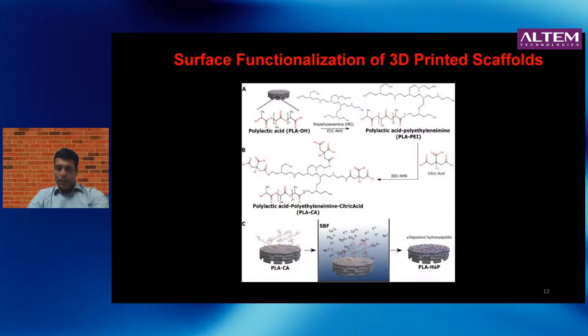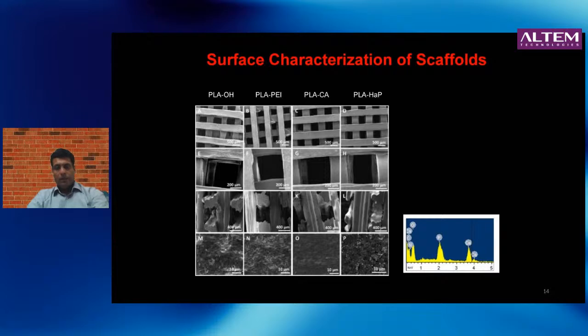Now, why citric acid? Because naturally it's present in small amounts in bone tissues, and its role is to help in the nucleation of calcium phosphate. So when we took the citric acid decorated scaffold and we put that in SBF, what we found was that there is hydroxyapatite getting deposited on the surface of this scaffold. And so what we did next was to study what the surface was of the as printed scaffold, and also after each of these steps of modification, all the way to the last step of hydroxyapatite deposition.